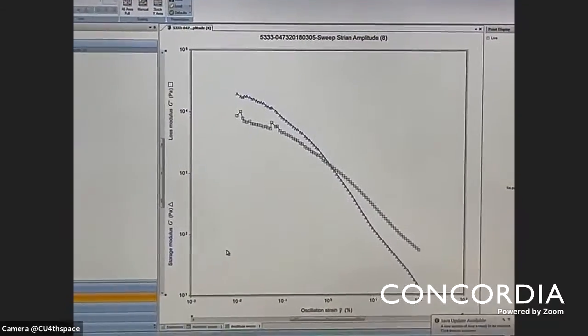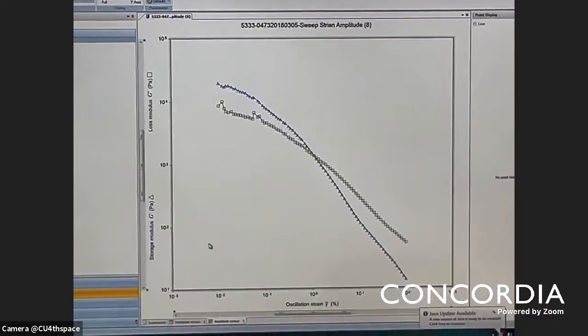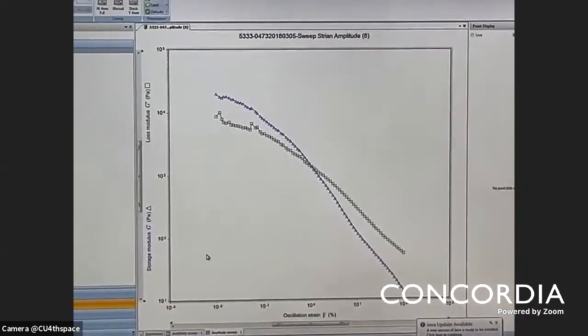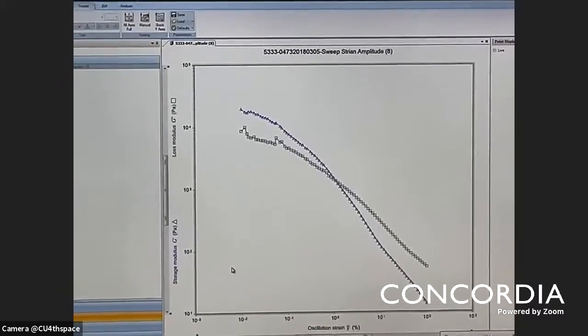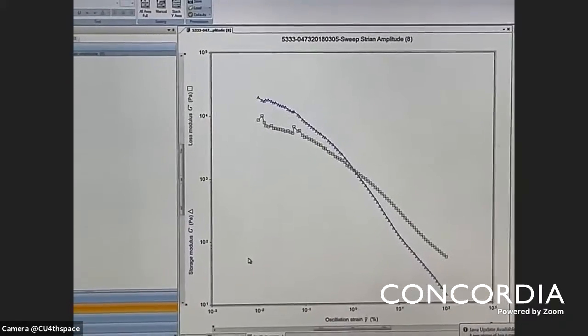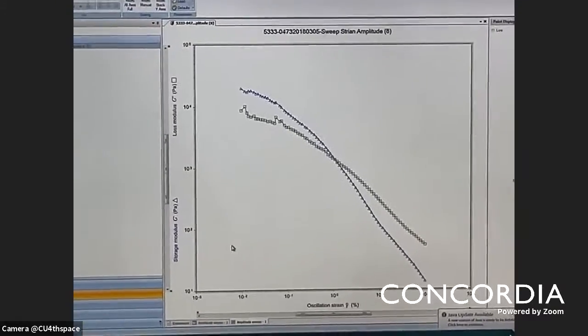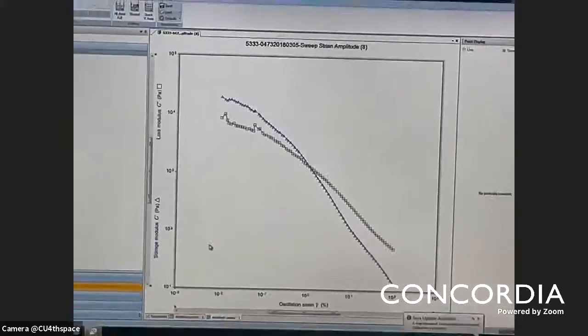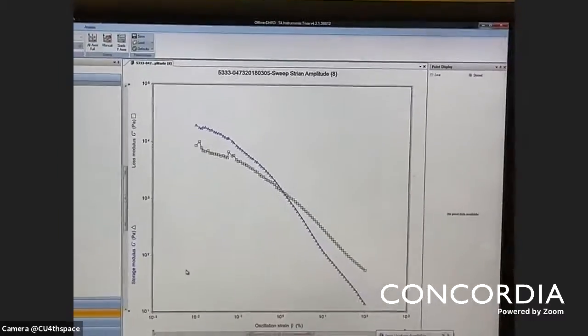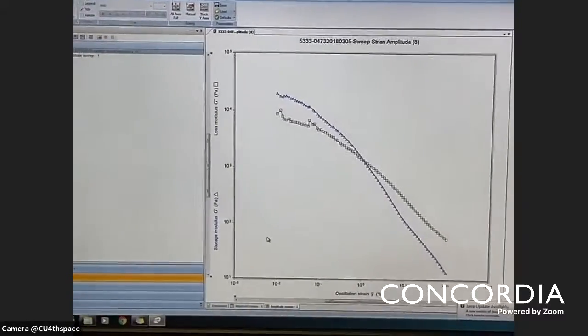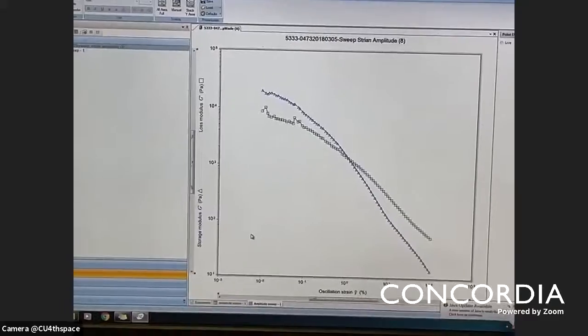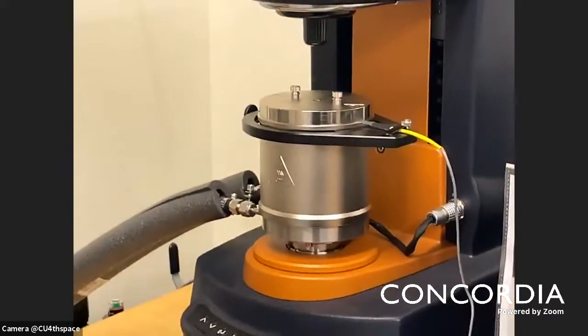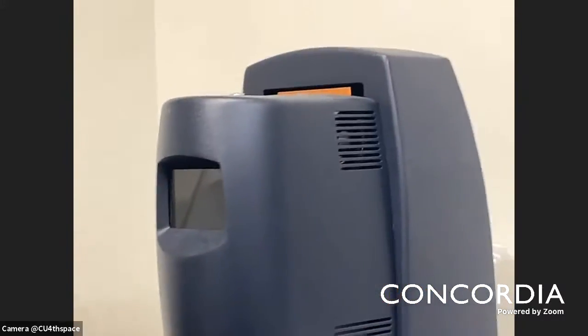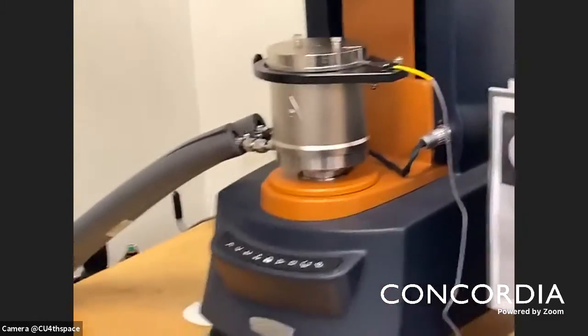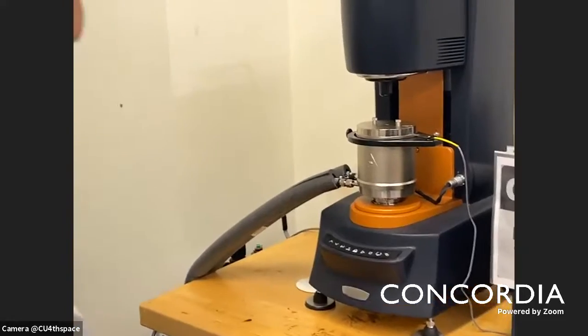We see here a storage modulus and the loss modulus. The storage modulus is the ability of the material to store energy elastically, and the loss modulus is the ability to dissipate heat. So we can predict the behavior of the material. Also, based on the experimental tests that we are doing in this laboratory using this rheometer, we can make a comprehensive mathematical model for this MR elastomer, and we can use it in our simulations to predict the behavior of the material.